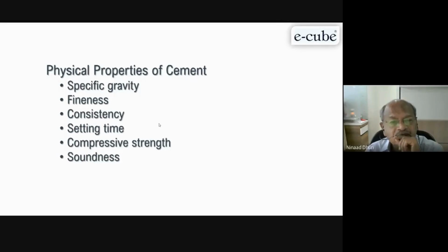But don't try to do cement testing at site unless you have proper arrangement for testing cement. In the sense, all the environmental conditions need to be met. Otherwise, a totally different picture will come. Even for compressive strength, they say that a particular source of sand has to be used. Currently we are getting it only from Chennai, quartz sand having minimum water absorption levels. So only that we have to use.